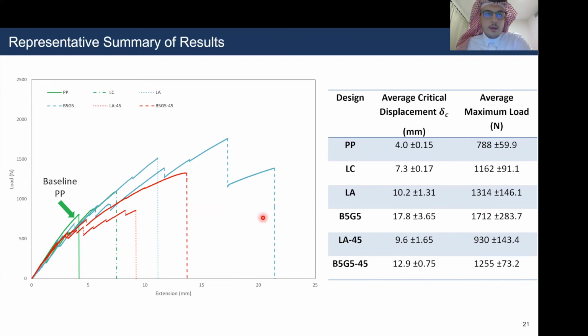So the blue dashed line here, which indicates patterning, B5G5 with the 0, produced a higher average critical displacement as compared to 45, and also a higher average maximum load as compared to 45. This was also confirmed with LA. So if we consider LA 0 degrees compared to LA 45 degrees, we can notice that the LA with the 0 degrees produced enhanced toughness as well.